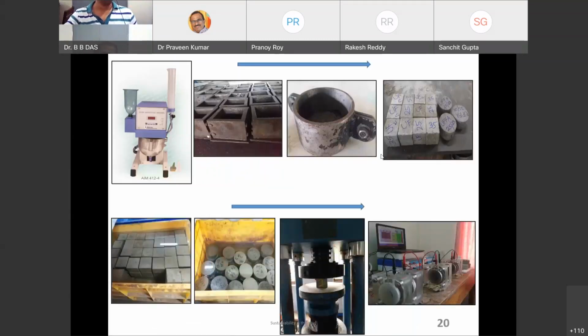Now you can see here, this is the procedure. This is my automatic mortar mixer, and here are the molds for the cube specimens, and this is the cylindrical mold for the acidity test. You can see after demolding, they were kept in the container for curing, and then they were tested. For compressive strength, this is the compressive strength test, and this is for the rapid chloride penetration test.